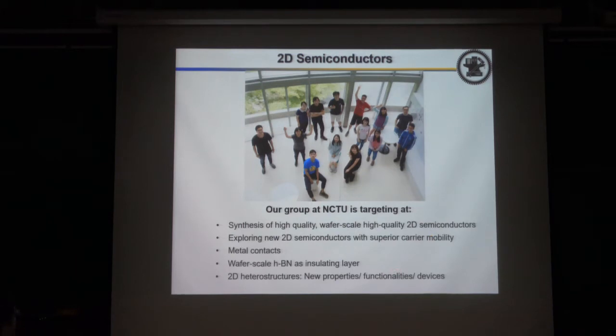Also, we are trying to explore some new materials with better carrier mobility, and we are trying to solve the metal contact problem, because typically the contact resistance is very large when you use a typical metal contact with the 2D semiconductor. This is the major bottleneck to realize practical electronic devices for industry. And you may know we were working on hexagonal boron nitride growth, and we have also tried to fabricate some 2D heterostructures.